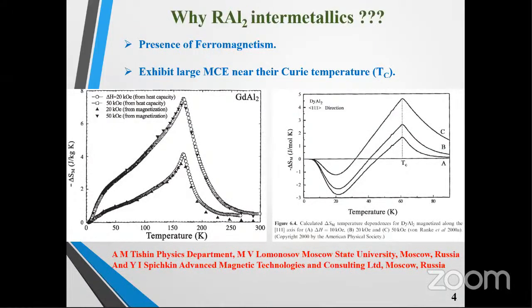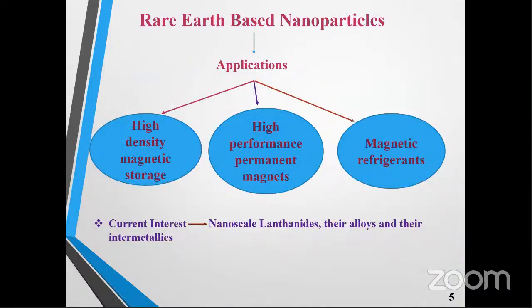So why have I chosen RAl2 intermetallics? Because they show the presence of ferromagnetism and they exhibit a large magnetocaloric effect near their Curie temperature. From the figure, we can see that GdAl2 intermetallics show a broad transition near the Curie temperature. Also the DyAl2 sample shows a broad transition near TC, which is a good property for a good magnetocaloric material. Now, rare earth-based nanoparticles have many applications like high-density magnetic storage, high-performance permanent magnets, and magnetic refrigerants. So the nanoscale lanthanides, their alloys and their intermetallics are of current interest due to their novel magnetic properties.